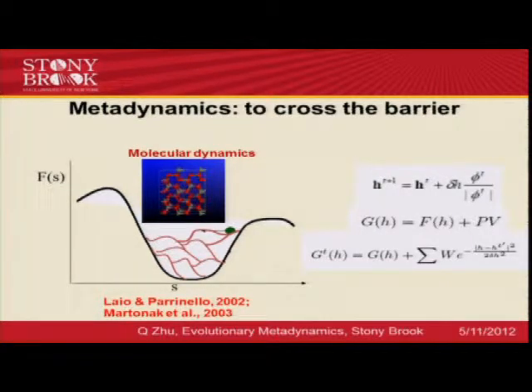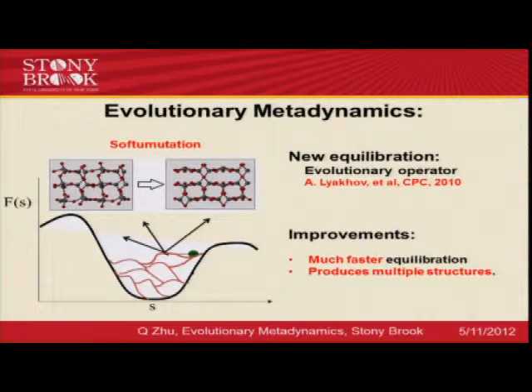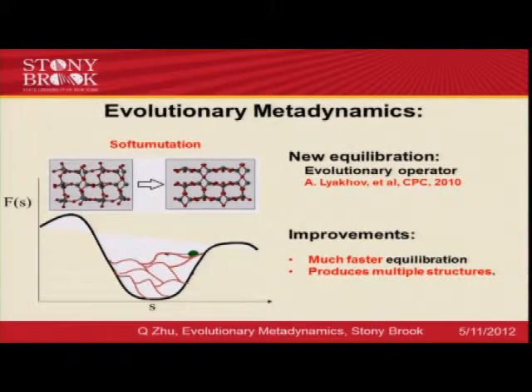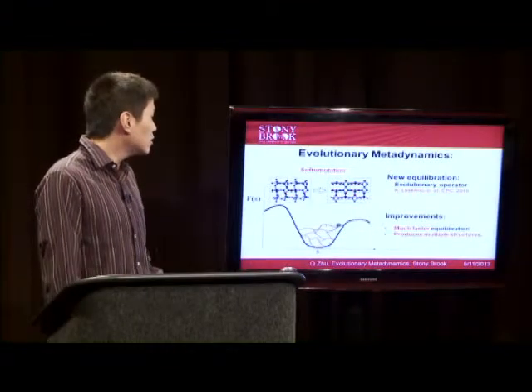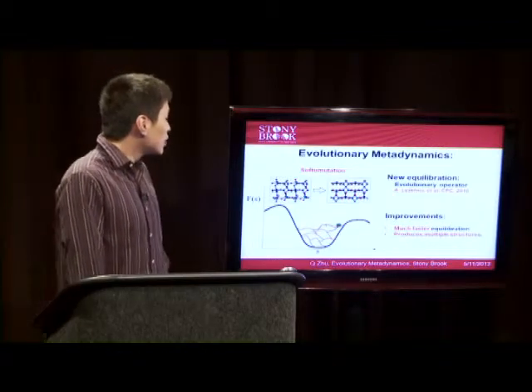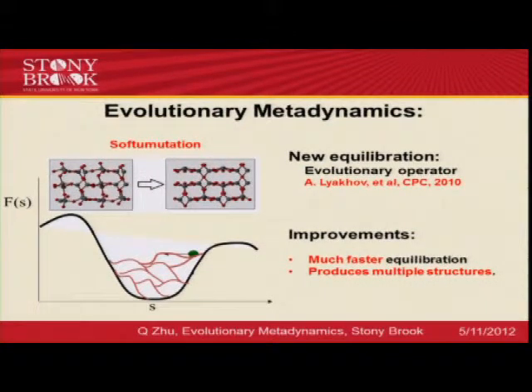However, as we know, molecular dynamics is usually time consuming. So we made an improvement for this method. The adjustment is small but very useful and important. We use new equilibration, but instead soft mutation from an evolutionary operator. The idea of soft mutation is to mutate the atoms in the cell according to the calculated soft modes.